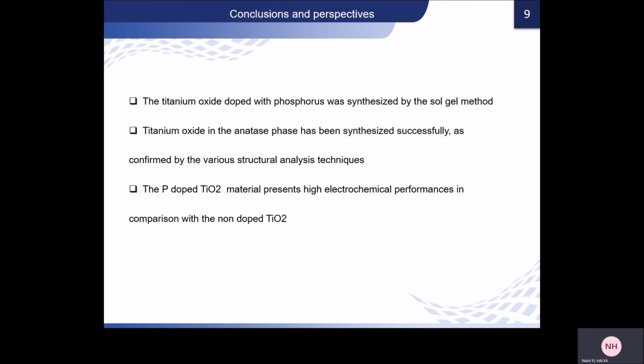Titanium oxide in the anatase phase has been synthesized successfully as confirmed by the various structural analysis techniques. The P-doped titanium dioxide material presents high electrochemical performance in comparison with the non-doped titanium dioxide.